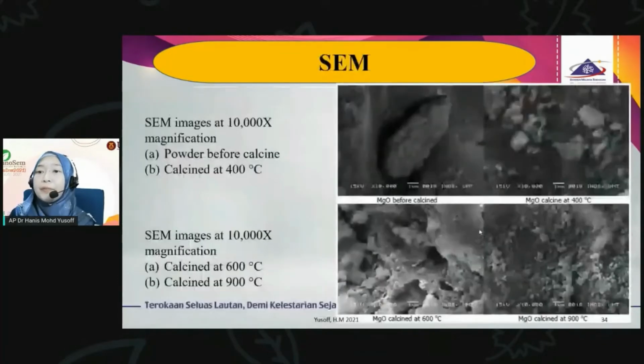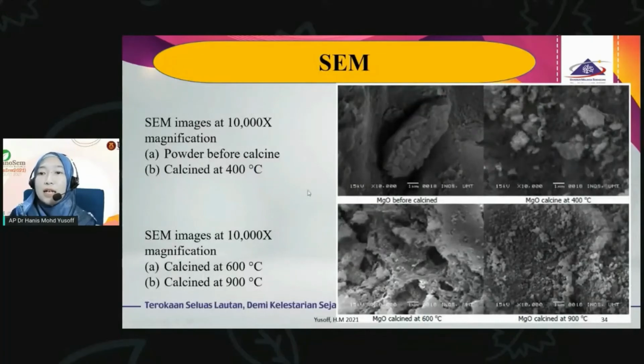Okay, for the SEM, here are several images, which is before calcination, and at 400, 600, and 900. So you can see here it is a non-homogeneous, irregular shape. However, as the temperature increases, the particles seem to be smaller, and the lowest that we could get is about 100 nanometers. So it's within the range, even though we cannot get smaller as in the previous study.